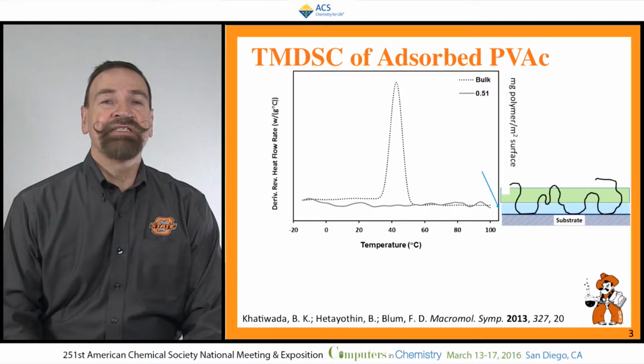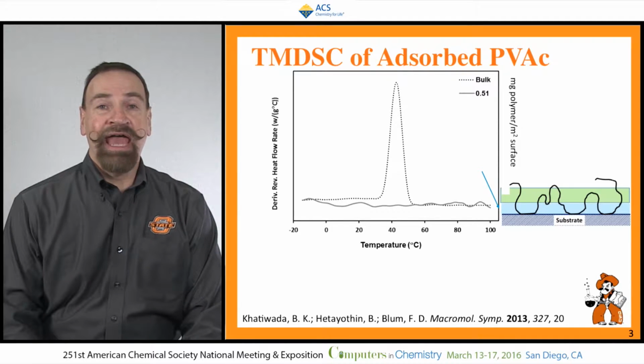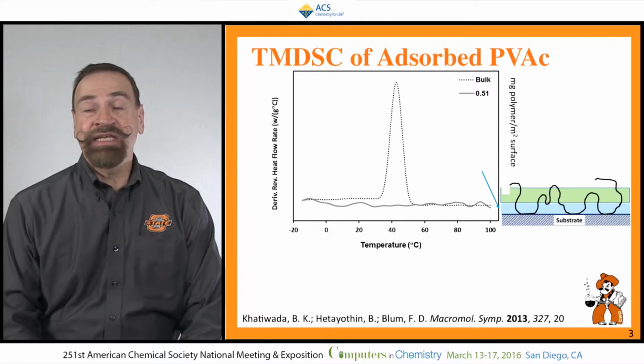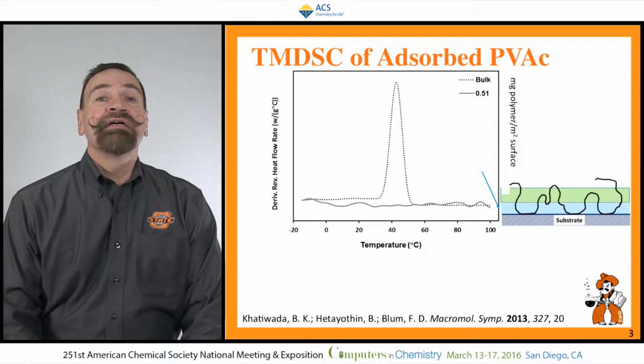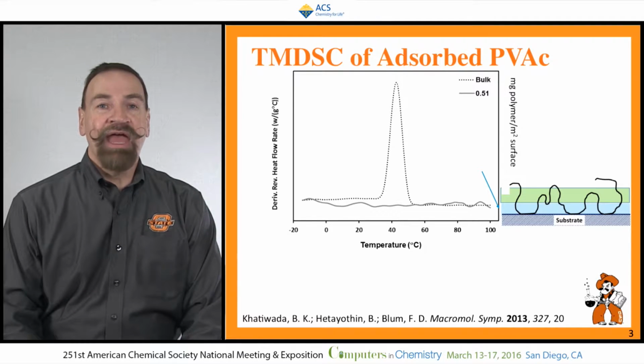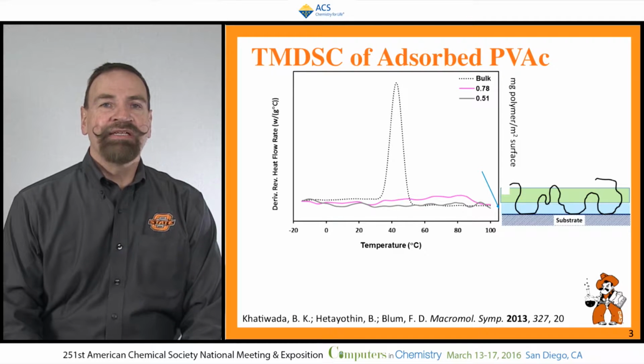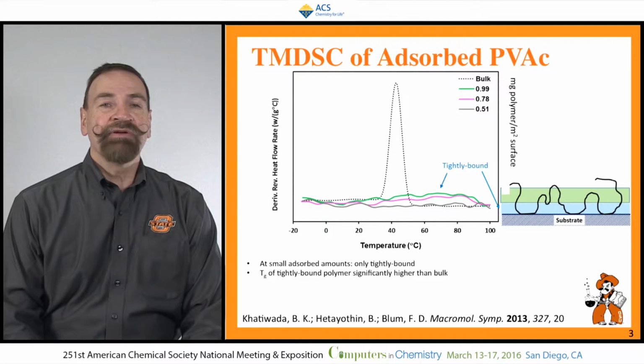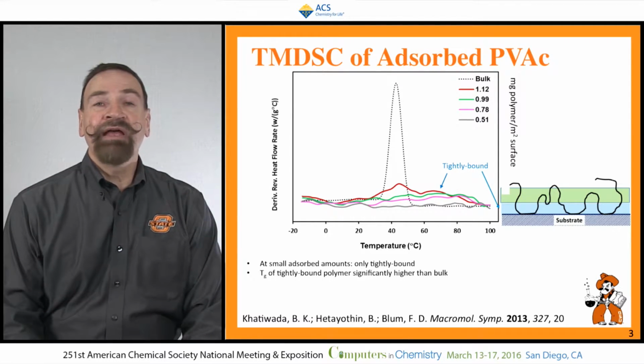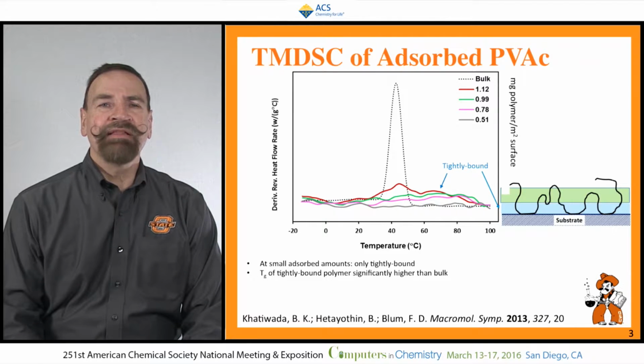If I take and add just a tiny amount of polymer to the surface of silica, what I see is very tiny or no calorimetric behavior. In other words, it just looks like baseline. As I increase the concentration a little more, now there is some thermal behavior that seems to occur in the region of 60 to 80 degrees. As I increase the polymer amount a little more, I see that there's more of it by the time I get to about 1 milligram per meter squared. And then when I'm up around 1.12, I see a peak that looks like bulk polymer.